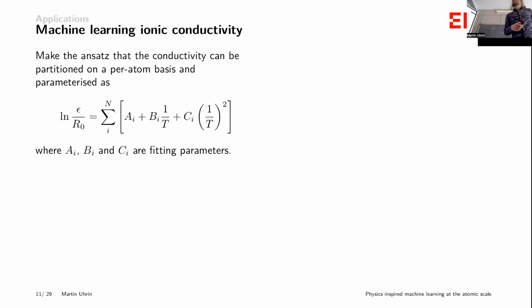So here's a part where I think is an example of where we try to inject some of the physics into it. So let's say I make an ansatz. I know that the conductivity is probably governed by the same kind of laws that we are used to, an Arrhenius equation. So instead of just letting the machine learning model learn anything that it wants, I'll say you have to learn something that looks like an Arrhenius law. I'll give you some parameters, A, B, C, that you can learn in any nonlinear way you want. And then I'll sum this, where i runs over all of the atoms in the system. So it's like I'm going to learn a contribution to the final ionic conductivity from each atom, considering the atoms that lie around it, and then add that with the next one, then the next one, then the next one. And the reason to do that is that that gives you locality.